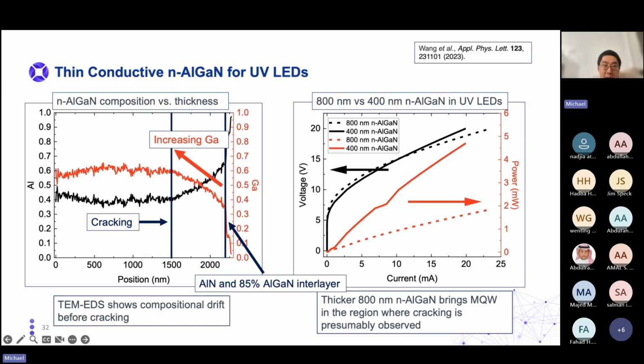And then when this gradient stops over here around 800 nanometers thick of n-type AlGaN, this is presumably when the material cracks, and then the gallium composition stabilizes. So since the material cracks at around 800 nanometers, I grew an LED with around 800 nanometers of n-type AlGaN, just to show that even if the material still looks fine, the microscopic cracks will destroy all efficiency in the LED. So between the 400 nanometer n-type AlGaN and the 800 nanometer n-type AlGaN, the light output power is decreased by more than a factor of 2.